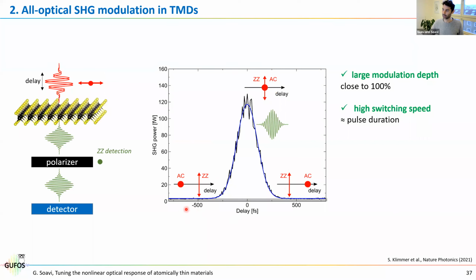Let me show this in experiments. So here on the x-axis, we have the delay between the pump and the probe. And you see that for long delays, we have one along armchair, one along zigzag, and there is no signal along the zigzag direction. And then as soon as the two pulses overlap in time, we have a maximum, and then it goes down to 0 again. What is the advantage of this approach? Well, the modulation depth is very large. We have 100% modulation depth in principle.